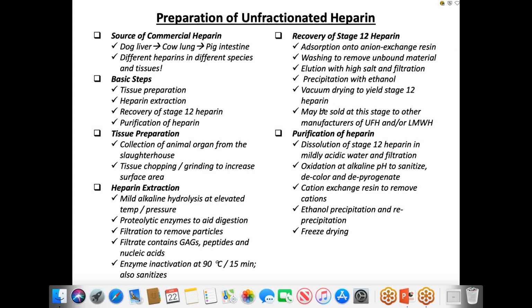Even at this point, heparin is still a mixture. Heparin is still a tremendously bad mixture, where only one-third of the chains actually have the heparin antithrombin binding pentasaccharide. At this stage, you test for its activity, and you adjust the activity against a standard, and you come to know, and then you say, this is the amount that you need to inject.